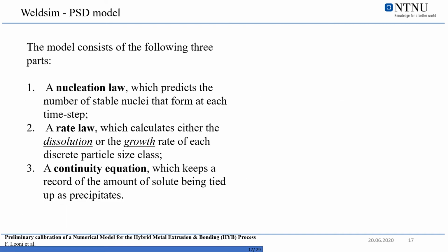The particle size distribution model consists of the three parts here presented. Basically, a nucleation law which predicts the number of stable nuclei that form at each time step, a rate law which calculates either the dissolution or the growth rate of each discrete particle size class, and a continuity equation which keeps a record of the amount of solute being tied up as precipitate.